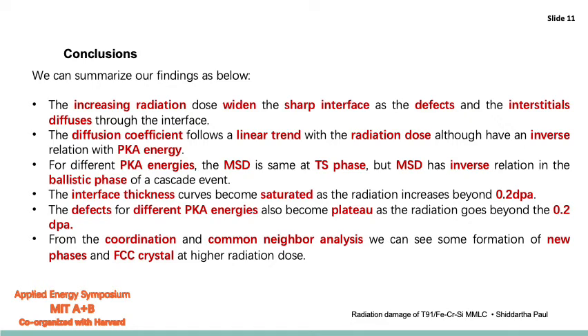And we have also seen the defect count for the primary knock-on atom energy become a plateau when the radiation dose goes beyond 0.2 dpa. After 0.2 dpa there is some kind of phase formation or phase transformation of the chromium and its neighboring atoms. So that's why it forms some new phases that suppress the defect formation and the widening of the interfacial thickness.